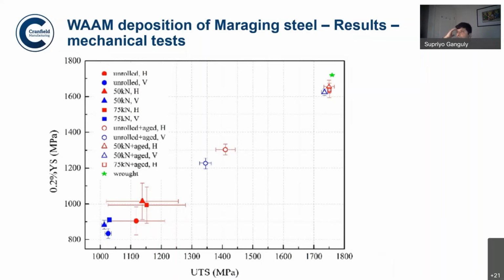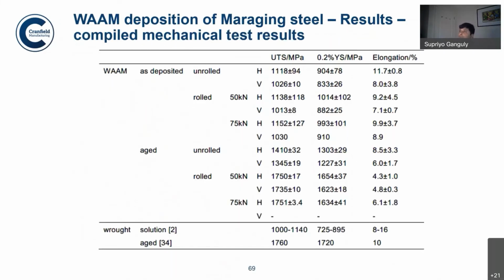So this is work being done on this maraging steel, which shows that even in this kind of high-end alloys, it is possible to maximize or achieve the optimized strength and toughness by implementation of cold rolling, which is a very important tool for wire plus arc additive manufacturing. So now I'm showing you the result of the work. The rolled with 50 kilonewton or 75 kilonewton both have a very similar effect, and here we have achieved strengths of 1750 and 1751, which is practically identical to 1760, and therefore it managed to get the same type of strength as the wrought and aged alloy.